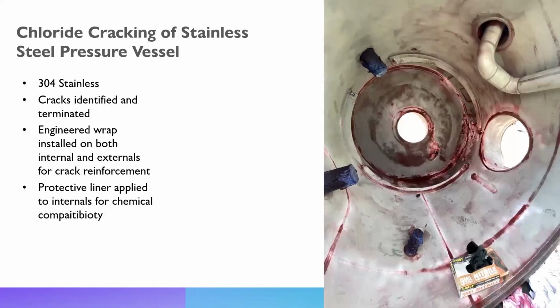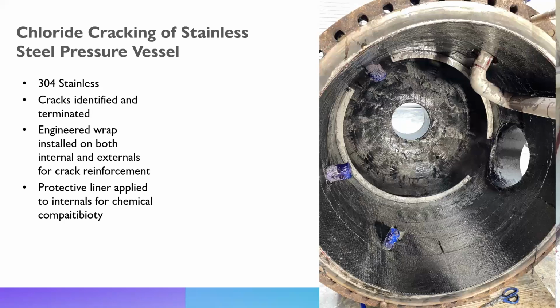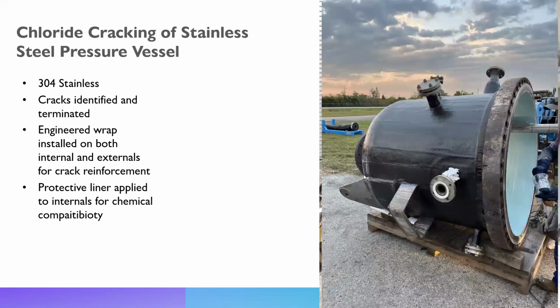So going into some examples, this is a 304 stainless steel pressure vessel, the head to a pressure vessel. It had several cracks right around here. We did a dye penetrant test to find them all and then installed an engineered wrap. We also terminated the cracks that we found. It was leaking in service, so they were able to take it out and do a good repair. So we did an engineered wrap on the inside and also on the exterior.